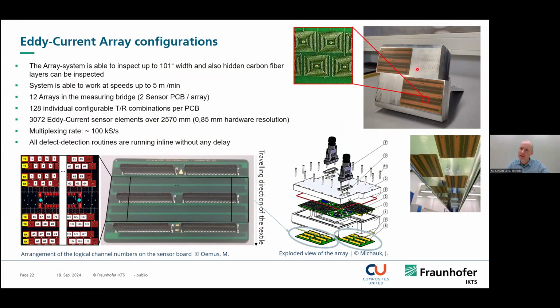So we have these 2 PCB boards. There's an overlapping area here, and we have different sending and receiving lines, and we generate different combinations to optimize the sensitivity in different layers. So we have 12 of these arrays, so 24 PCB boards, and we can generate 128 individual transmitting receiving combinations on one PCB. In sum, there are over 3,000 eddy current channels at 101 inch. And there's a multiplexing rate of about 100 kilosamples per second. So that's mostly the fastest and longest eddy current array in the world.